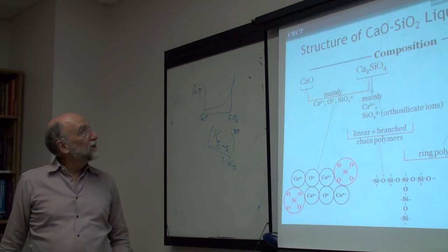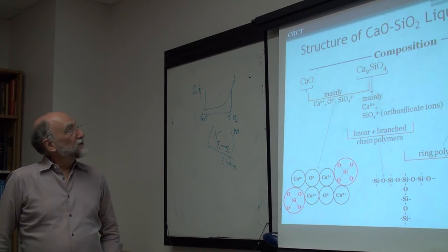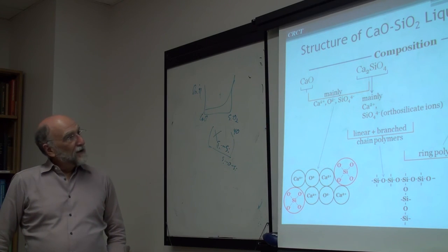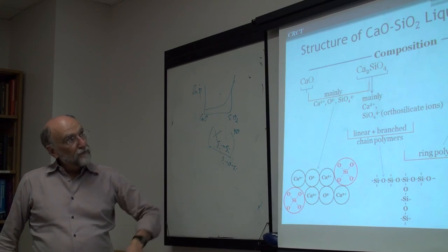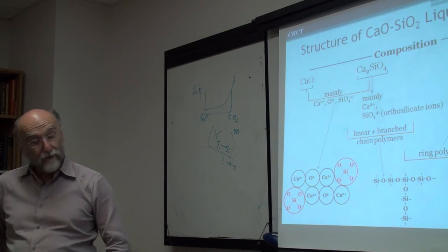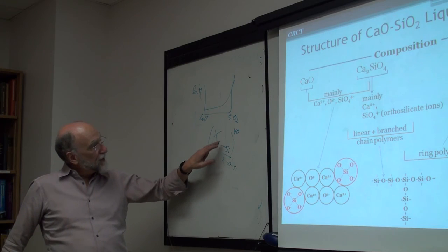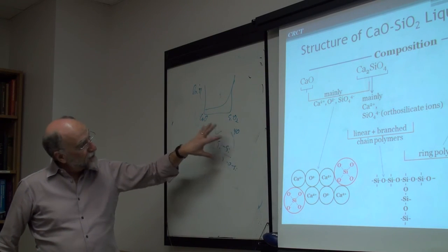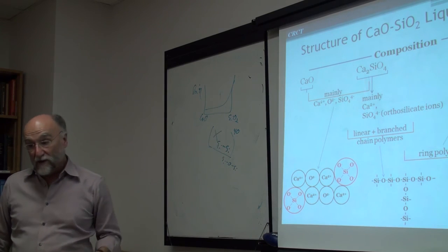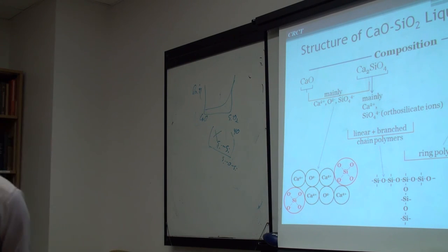I can't go into the viscosity papers here, but basically we start with the quasi-chemical model, which was optimized from the thermodynamic data. We use the silicon-silicon pairs that have been calculated as the concentration unit for the viscosity model. It seems to work pretty well.